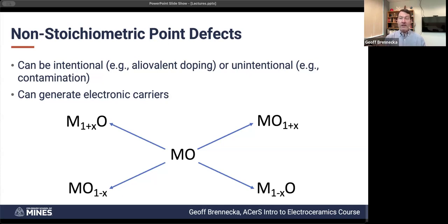If it's a vacancy, maybe an oxygen vacancy, in most of the ceramics we care about, the oxygen sublattice is close packed. So it's easier for oxygen vacancies to hop from site to site to site. But each one of those is going to have their own temperature dependence. And you're going to have different kinds of other barriers that might get in the way. So maybe you run into a grain boundary, and that particular grain boundary is such that it's really hard for the oxygen vacancy to get through. Or maybe it's a superhighway for the lithium to conduct.